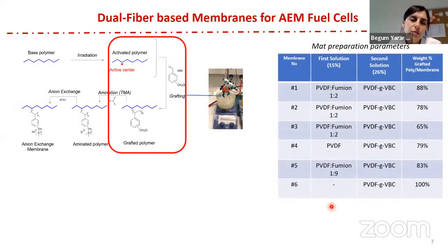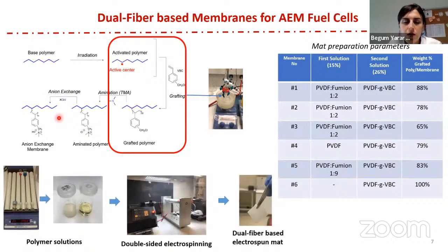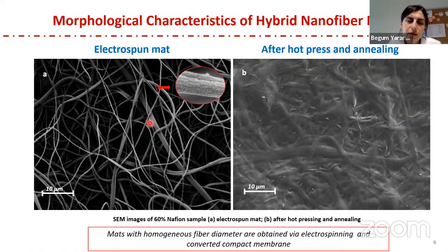I would like to show a little bit more about the second project. In the second project, we synthesized the anion exchange polymer using radiation-induced grafting, and after we synthesized the anion exchange polymer, we combined it with the inert polymer PVDF, and we used this double-sided electrospinning setup and obtained a dual fiber-based electrospun mat. Here is the content of the obtained membranes. Again, similarly to the previous study, we convert these electrospun mats to dense membranes with hot pressing and annealing steps, and then we characterize all of them.